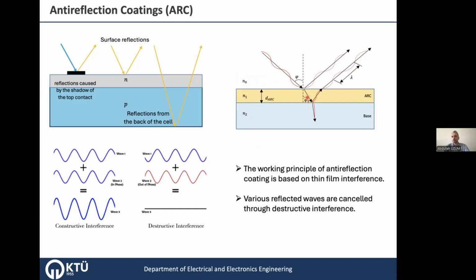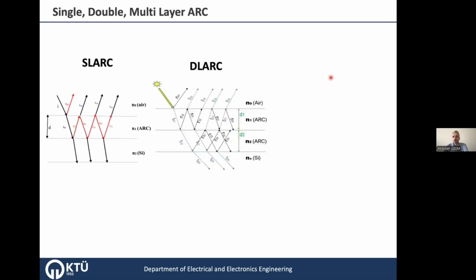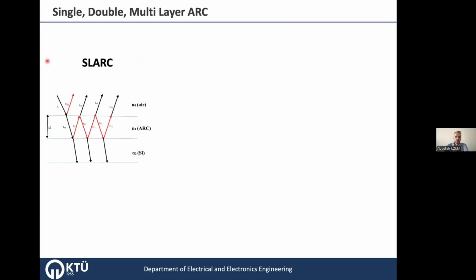And if you have this kind of destructive reflectance, then the reflected light here will be zero. But the zero reflection happens at only one wavelength, with a thickness of 1/4 of the specific wavelength you have. But we can make better reflections. This is the single layer anti-reflection coating.